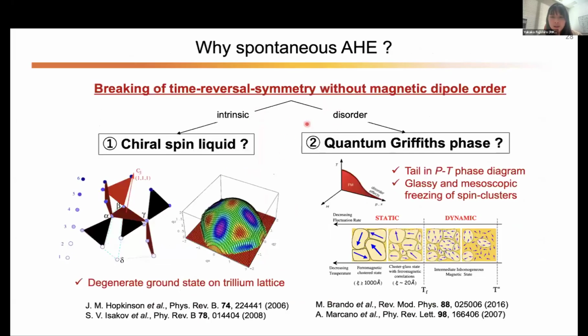So we're still investigating the origin of this anomalous Hall effect, but again, the breaking of time reversal symmetry without magnetic long-range order is very unusual. So one possibility is the chiral spin liquid state, because the B20 lattice has some extent of the spin geometrical fluctuations, which can generate a degenerate ground state. And another possibility is that